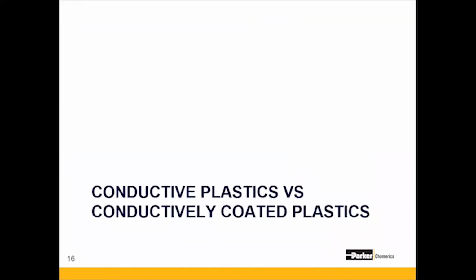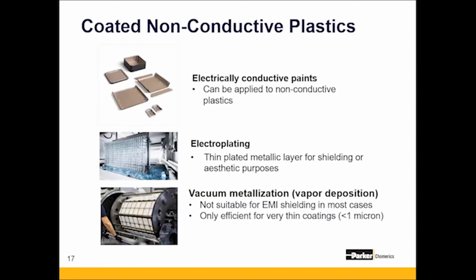Nice. The next thing we want to talk about is the comparison of conductive plastics versus conductively coated plastics, and what those applications look like. In addition to conductive plastics, there are non-conductive plastics that can be plated or have coatings applied to help them meet some EMI or electrical standards. The most common one is taking a non-conductive plastic and coating it with an acrylic, a polyurethane, or an epoxy-based conductive paint. Conductive paints are the most cost-effective solution to apply onto large surfaces and flat panels for EMI shielding. A lot of that comes back to the fact that, like we mentioned before, it's very difficult to mold large surfaces and flat panels in conductive plastics.